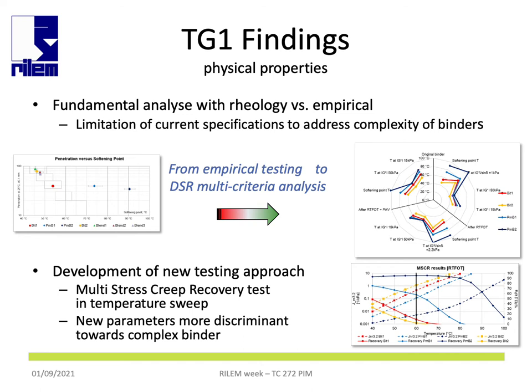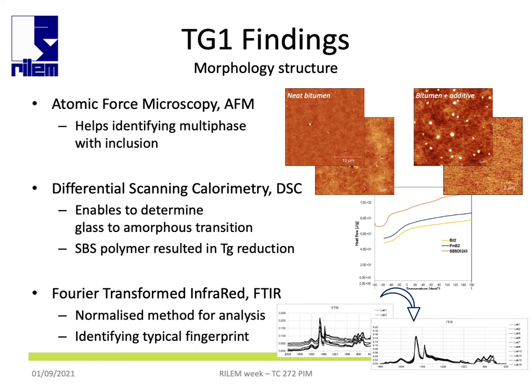An interesting finding from the TG1 is the multi-criteria intrinsic analysis derived from complex modulus measurement at several temperatures using a dynamic shear rheometer. And also the development of a new testing approach based on a Multi Stress Creep Recovery test in temperature sweep, which appears to be more discriminant for complex binders. Moreover, physicochemical analysis with atomic force microscopy, differential scanning calorimetry, and infrared spectroscopy has given the possibility to identify inclusions, to determine glass transition, and identify typical fingerprinting.